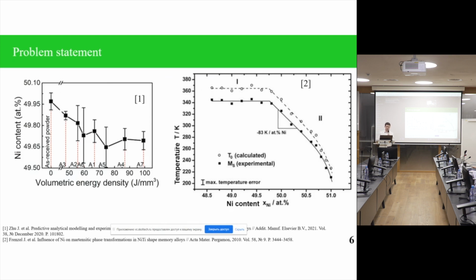So in many papers, it was demonstrated that after this 3D printing, the chemical composition, the nickel content, was reduced. And this circumstance in turn led to a shift in the transformation temperature. There is a well-known dependence of the transformation temperature on the chemical composition. This dependence was verified many times by many authors in different papers, so we can rely on it.